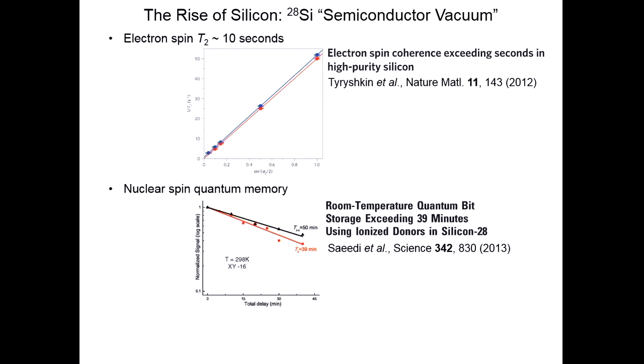This is another experiment from Mike Thewalt's group, a few years back, where they took isotopically enriched silicon, I think it was doped with phosphorus, and they did a process called electron nuclear double resonance, where you can transfer coherence from the electron spin state to the nuclear spin state. And they showed that they could make a quantum memory that had a lifetime of, I think, like 40 minutes at room temperature and several hours at low temperature, right? So all of a sudden, this is real. And in a solid state system, we have access to coherence times that I think you'd only see in trapped ion systems, right? Extremely clean, ultra high vacuum conditions, and in our dirty semiconductors, we have a chance of getting to that scale in terms of coherence.